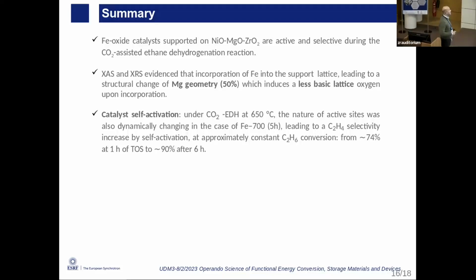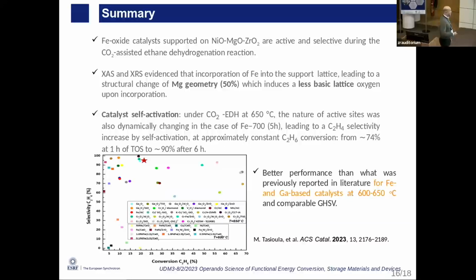More interestingly, we see that there is this catalyst self-activation. Actually, if we look at time on stream, we see that after 74%, we go to 90% after 6 hours, and this is also stable. As a result, our catalyst, with respect to the our material, which is this one, has better performance than the iron gallium based materials that people are still working on.